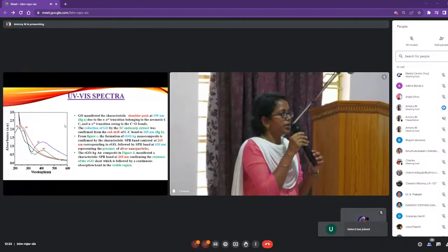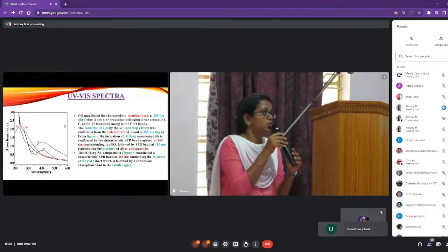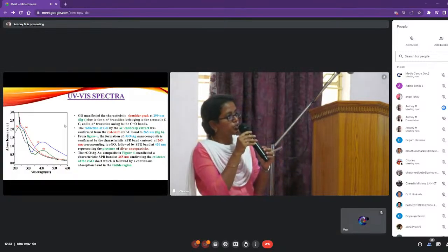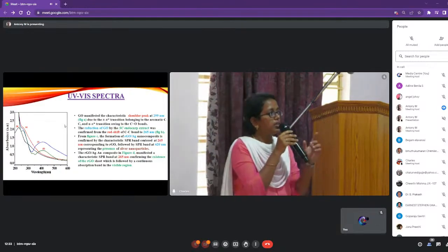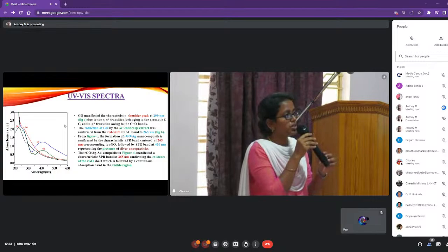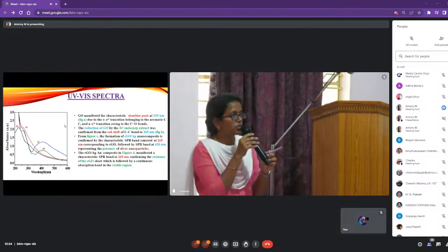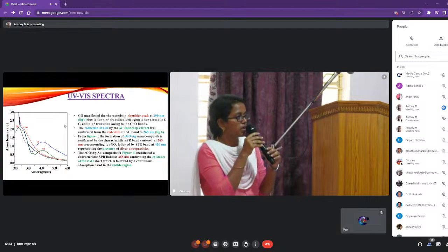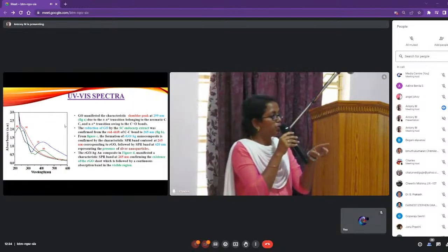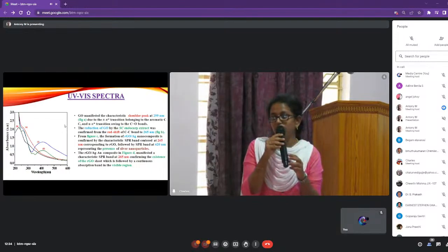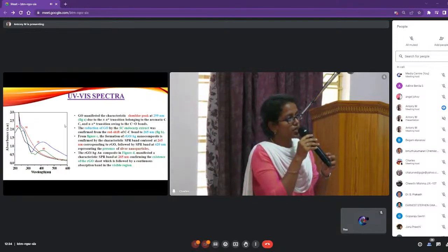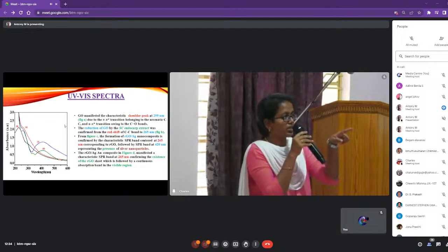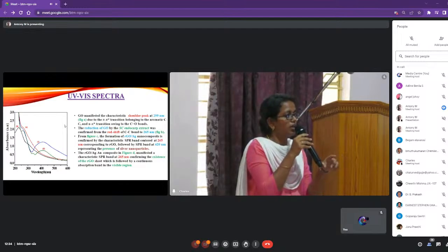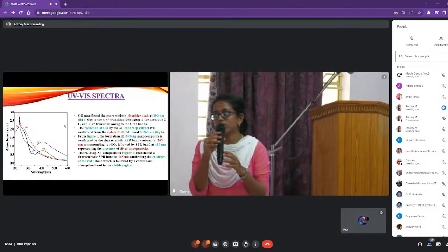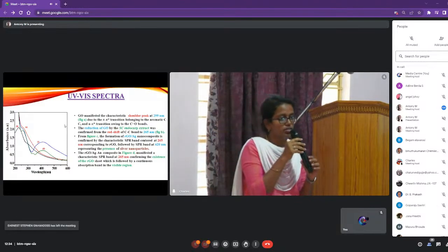So in this UV spectrum, the A, red, indicates the peak of graphene oxide, which exhibits the carbon-oxygen bond due to the n to pi star transition, and the B shows the presence of reduced graphene oxide, which has a peak at 265 nanometers. The C, which is blue in color, indicates the presence of reduced graphene oxide Ag, the presence of silver at 265 nanometers and 420 nanometers, and the D, which is green in color, indicates the presence of reduced graphene oxide Ag and Au nanocomposites.